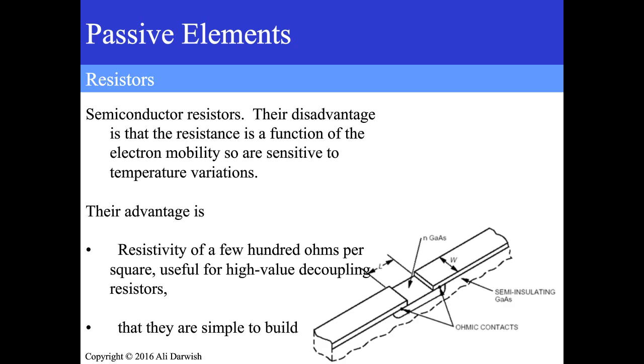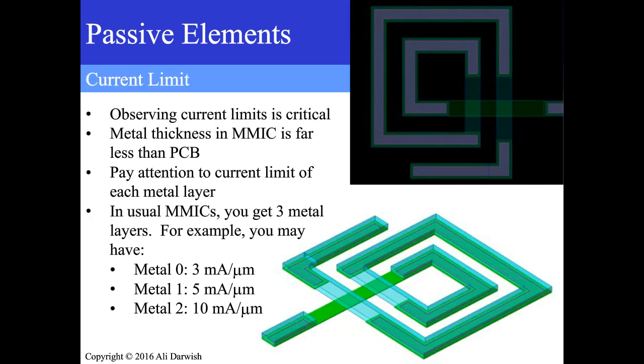Resistors that are based on the substrate typically can handle much more power, but their disadvantage is that their value is not so constant with temperature. So as you change the temperature, their value is going to change. So they're usually just good for decoupling, not so much for specific values of resistance.